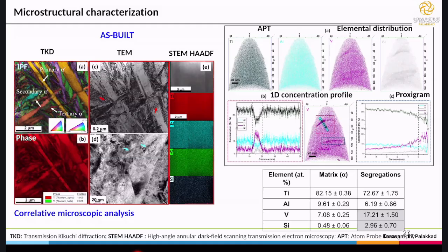Segregation is a kind of clustering of particular atoms, and that is happening because of the high cooling rate. Such clustering is taking place at the nano level. We need to look into how this clustering changes with heat treatment. If you look at a generic EBSD structure, which includes TKD, and a TEM structure, we don't see that, but we can see it with the APT structure. APT is atom probe tomography, an advanced microstructural characterization technique. So the takeaway is there is a segregation.